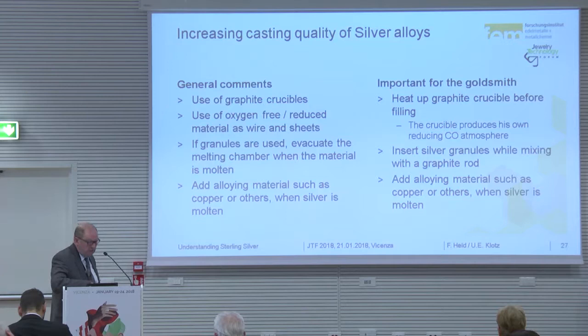For the goldsmith, the question is how he can make high quality in small batches. Heat up the graphite crucible before filling the material. The crucible produces its own reducing CO atmosphere. Insert silver granules while mixing with a graphite rod, so the oxide goes out of the silver melt, and then add alloying material such as copper or other when the silver is molten.